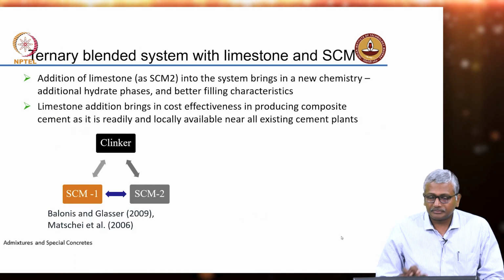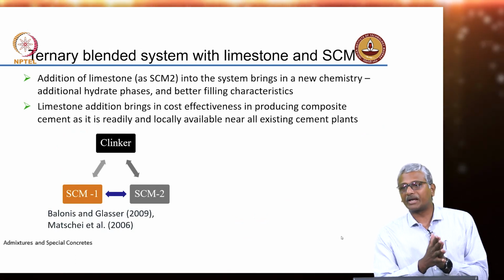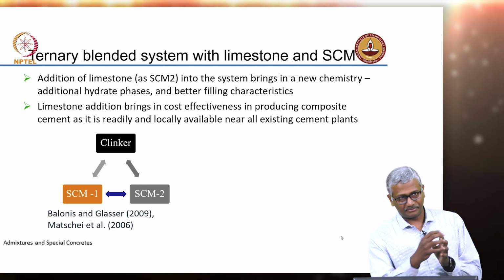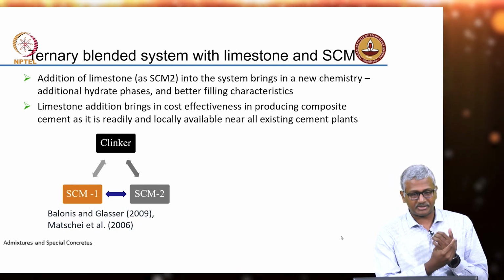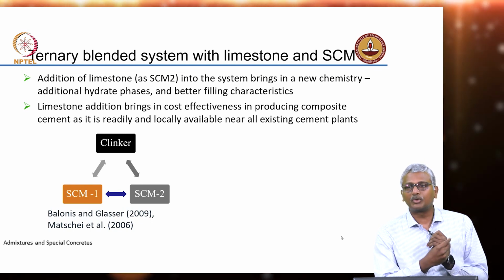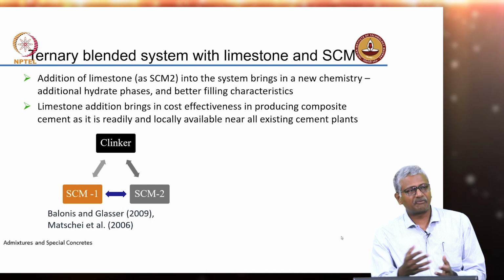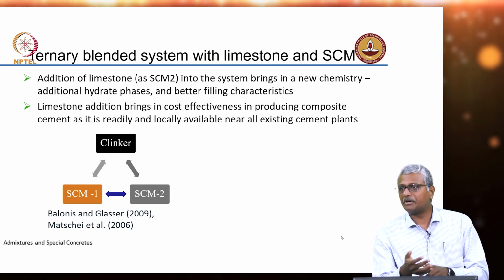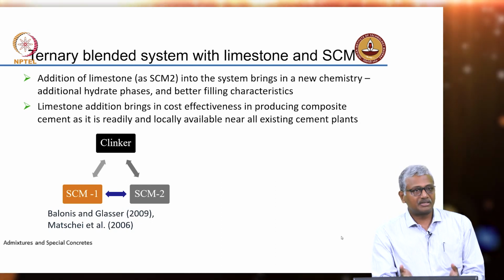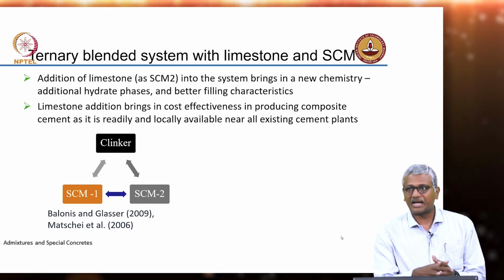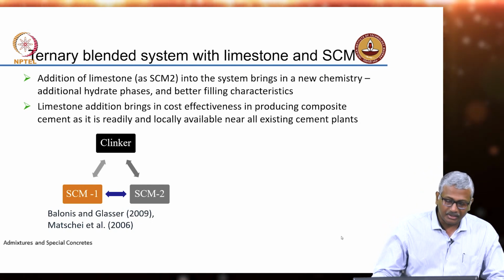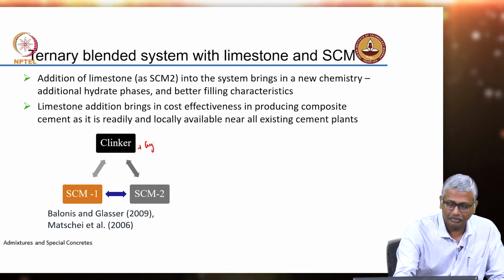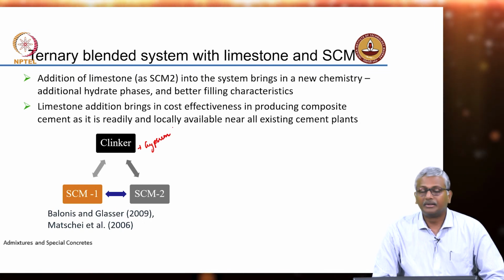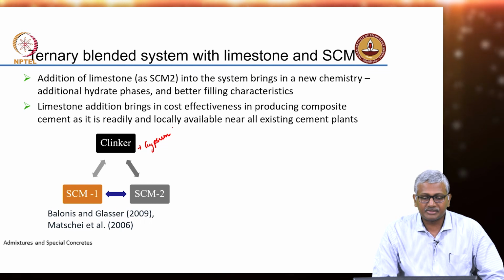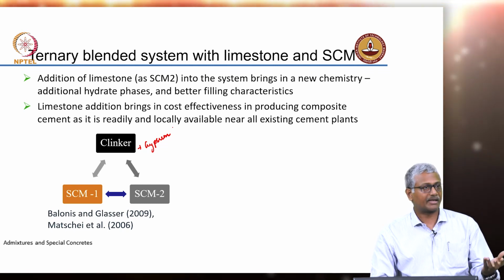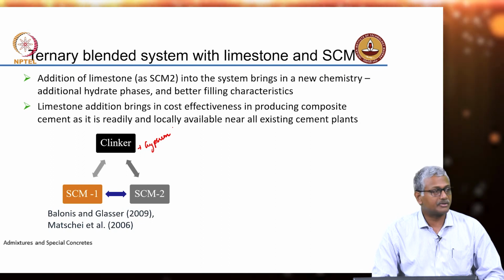Right. Now, moving on, we really want to look at this system where limestone can interact with a second supplementary cementing material. So here, what we want to do is try out a new chemistry, about which we've discussed primarily earlier, based on the availability of calcite to react with the aluminate to form carboaluminates. So the idea is to have a ternary blended system where you have cement clinker, and of course you also have gypsum, right? And you have two supplementary cementing materials. One is of course your fly ash or slag or calcined clay, and the second supplementary material is your limestone.